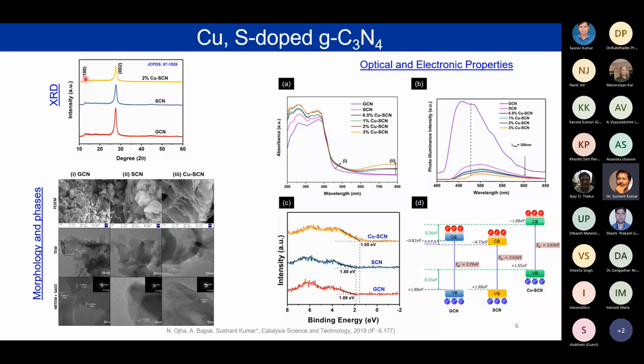I'm not able to show you here, but you can see that the intensity of these peaks has weakened, and there is a shift of the 002 plane towards the higher angle. That means there is a reduction in the interplanar spacing of the graphitic carbon nitride. And the second peak, shown here as 100, shifted towards the lower angle when we have 2% copper in SCN. SCN refers to the sulfur-doped graphitic carbon nitride. That means there is an increase in the void-to-void distances, where the sulfur and copper are doped in the plane and reside in the plane of the graphitic carbon nitride.